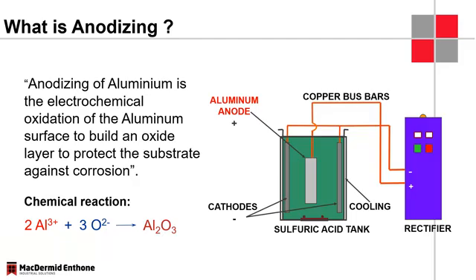If we look on the right here, this is a schematic of an anodizing tank. We have the extra aluminum part as the anode, where we generate oxygen for the oxidization. Then we have the cathode sheets, which could be lead or aluminum itself. And all this happens with the current from a rectifier in a predominantly sulfuric acid solution.